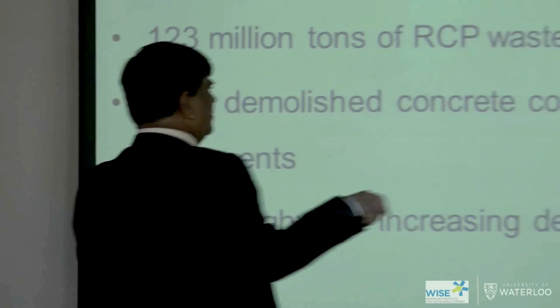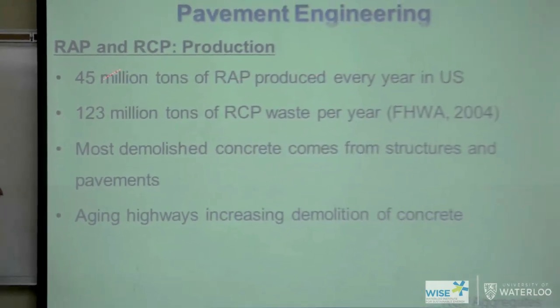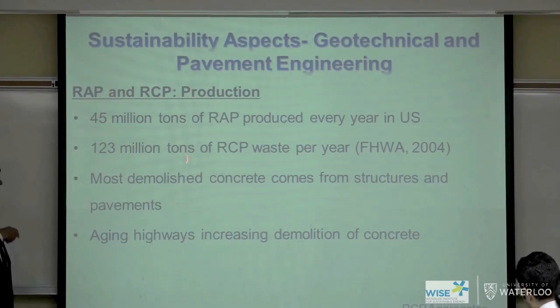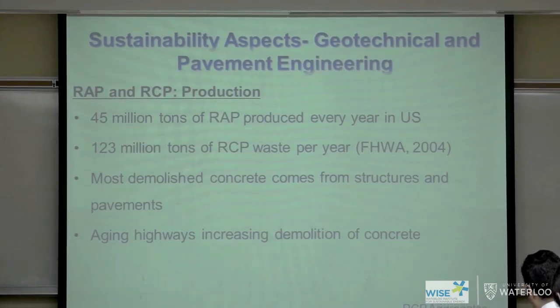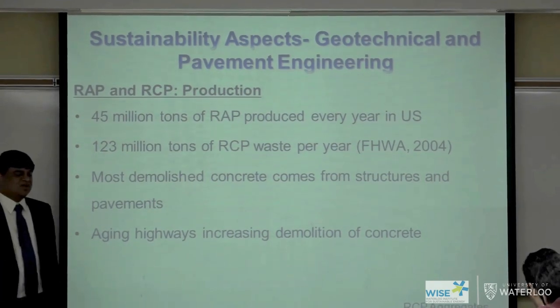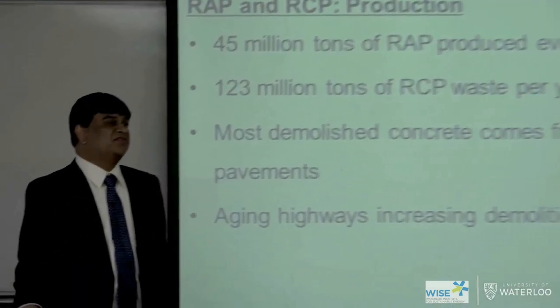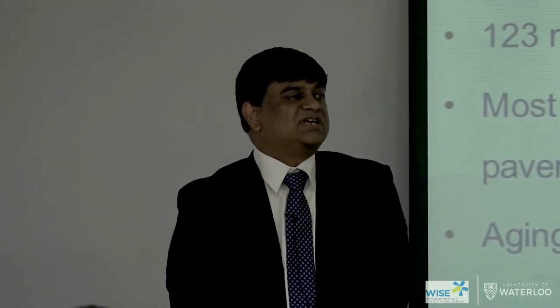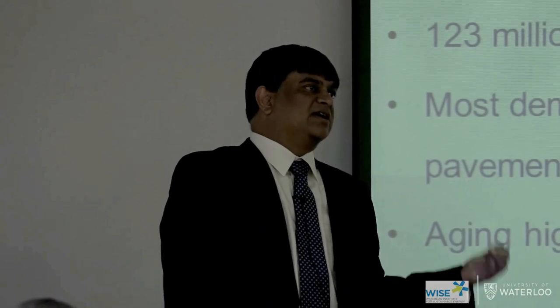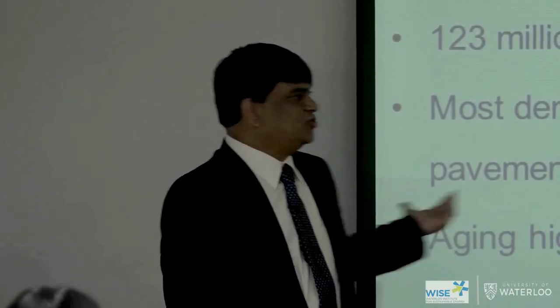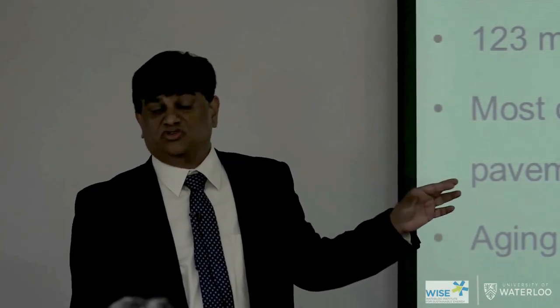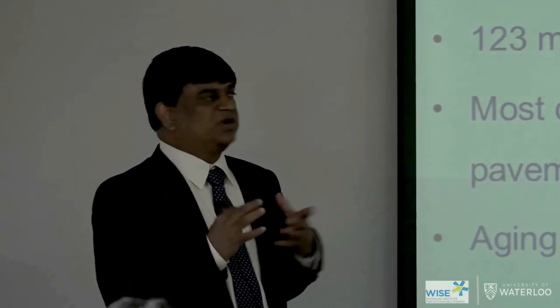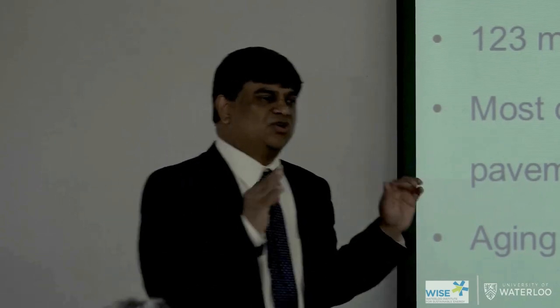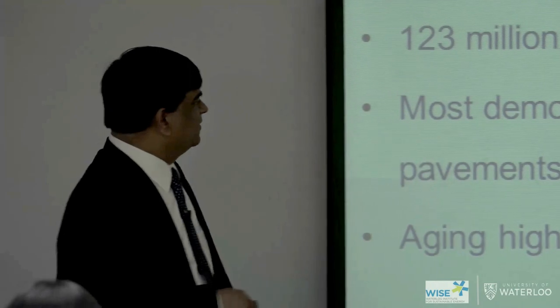So you have to look at all these things, but there are areas where this can work very nicely, okay? So if you look here, again, I'm sorry, I don't have Canadian numbers, but I'm pretty sure it's quite similar. 45 million tons is produced, a lot of waste. And again, we were looking for more and more areas of application. One area of application is MSE wall backfill material. In a lot of retaining walls, the backfills are typically a non-plastic material. Can you use an aggregate base? Can you use some of these materials? You could, provided it works well with all the properties you're looking for, and that is a good application as an MSE wall backfill material, okay?